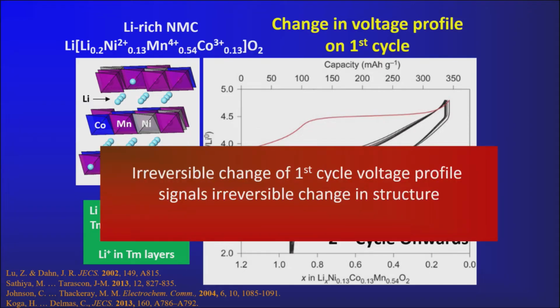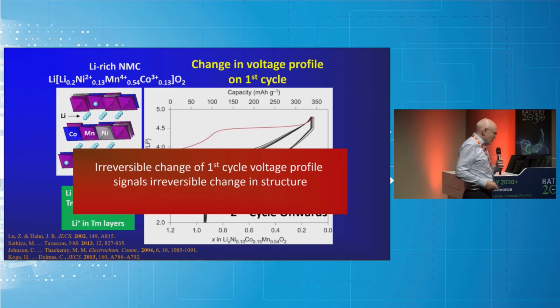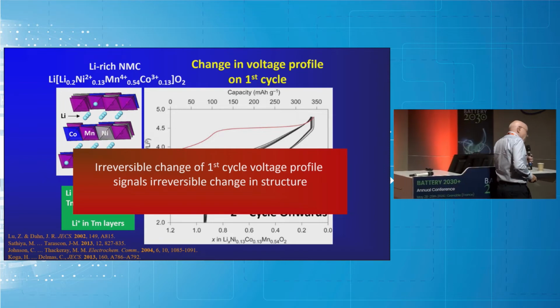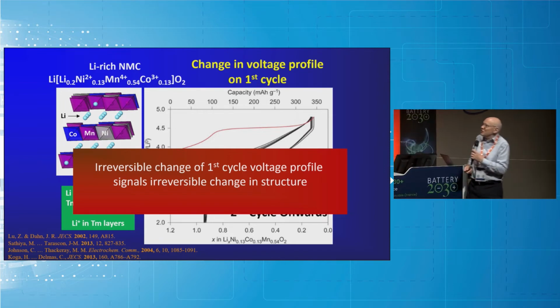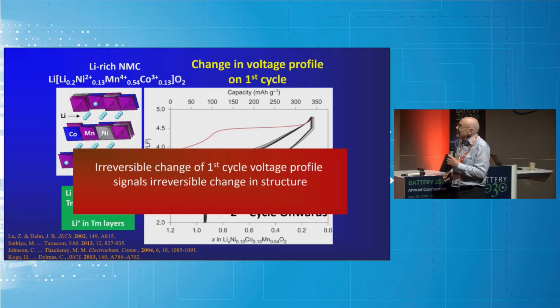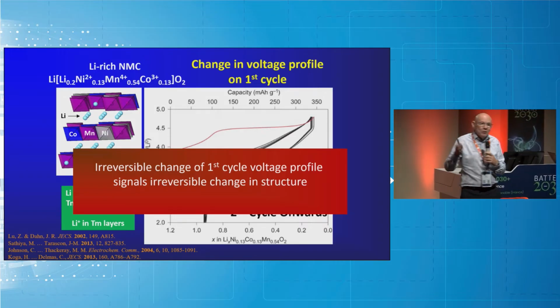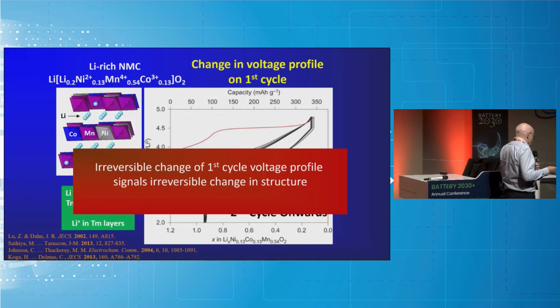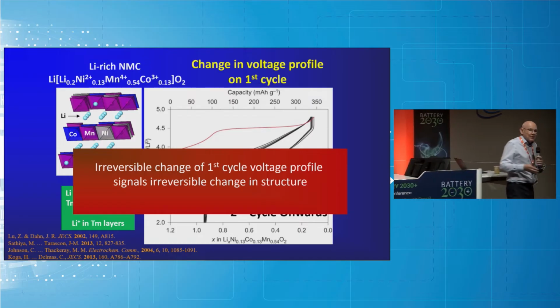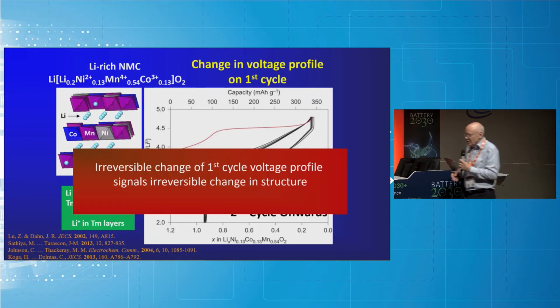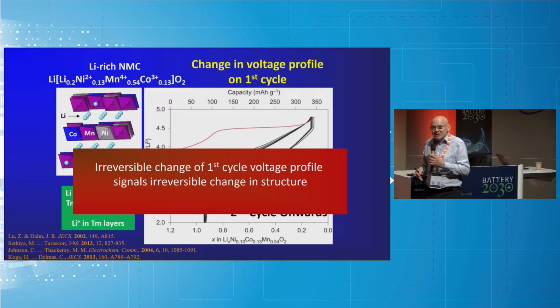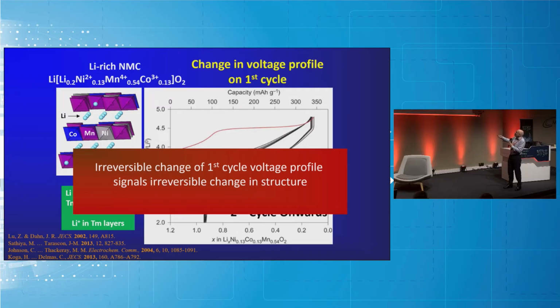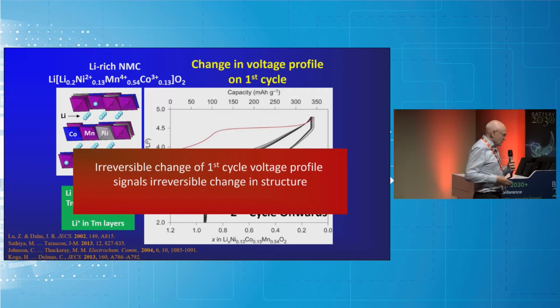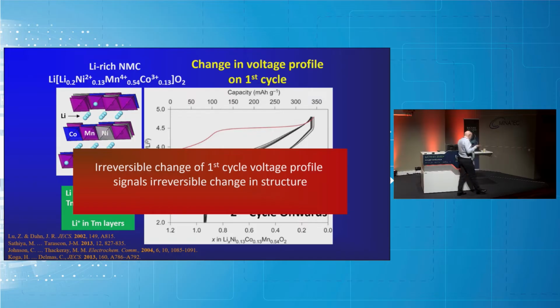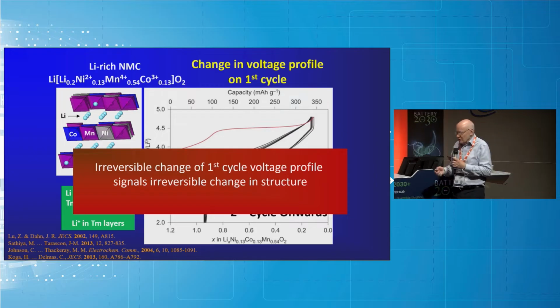And so the message is there's a big change in the voltage. That means a big change in the structure is taking place. All these things we really don't want to happen. But if we're going to be able to stop those happening, we have to understand what's happening to the oxide ions when we carry out oxygen redox. We know the lithium ions come out. That's easy in that region here. The question is, what is happening to the oxide ions? So in other words, we really need to study the evolution of the electronic structure of oxide ions when you strip electrons from them.